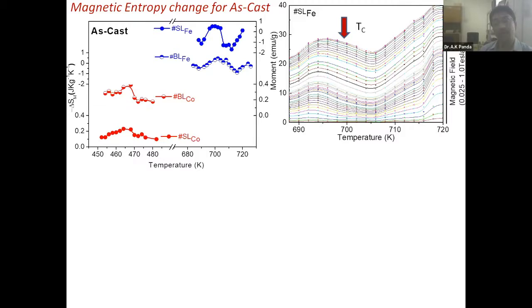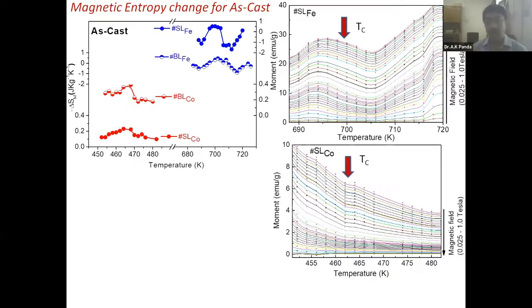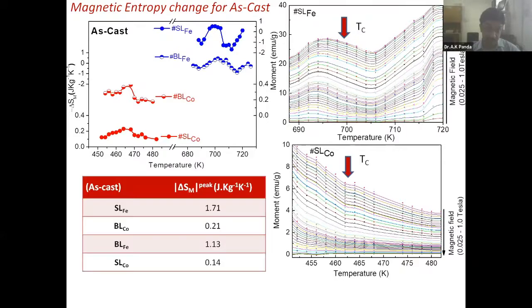And this is the moment versus temperature, where the arrows indicate the Curie temperature of the alloys. And it is for the single layer cobalt that goes on decreasing, as I told you earlier. This is how the moment versus temperature is obtained. Now this is a simple display of the entropy, the magnetic entropy. You see that the single layer entropy is 1.7.